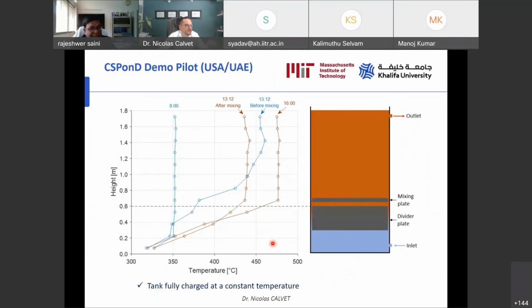Another way to represent this result is to plot the height of the tank as a function of temperature. So you see at the beginning of the day at 8 o'clock, you have a temperature of 350 in the tank, homogeneous. And then at the end of the day, at 4 o'clock, you see that all the useful volume of salt is at, let's say, 480, something like that. Okay, so we are able to charge the system using directly irradiated molten salt, which was demonstrated for the first time in the world. So we are really proud of this project.